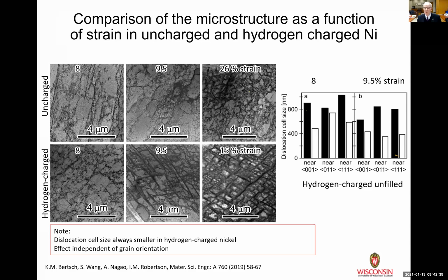So as we go up and we say, well, can we see it in more than one material? This again is an example from nickel. We're looking at the same level of strain. And I must admit, now looking at this figure, I forgot to put the grain orientation on the sample. One of the challenges in electron microscopy that we face is people can always say, well, the microstructure that you see depends on the grain orientation. And they're absolutely right.